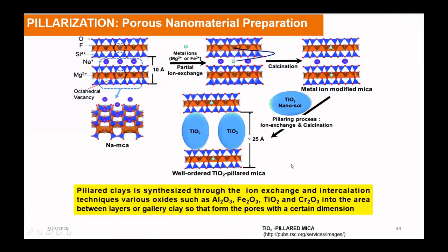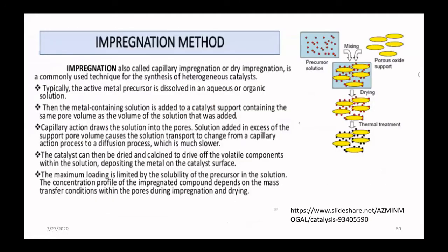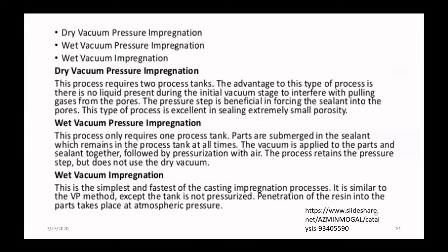Okay, this is an example. And the impregnation method for making supported catalyst is quite easy. The precursor solution is mixed with the porous oxide, and after that drying, followed by thermal treatment, and sometimes reduction, oxidation and reduction. This is an example of impregnation: dry, vacuum, wet, vacuum, etc.